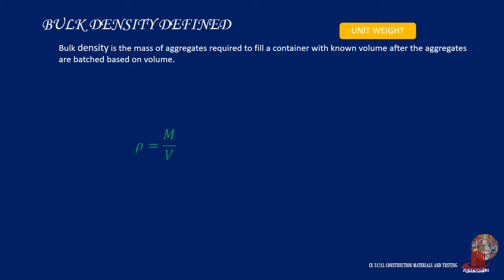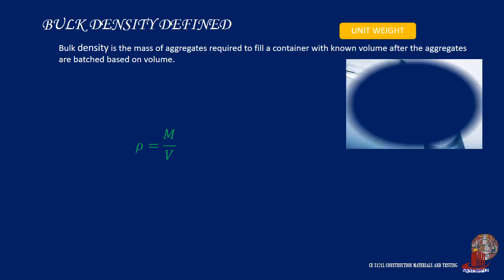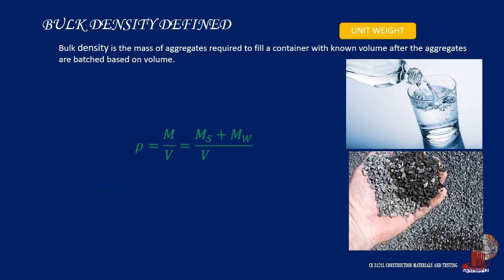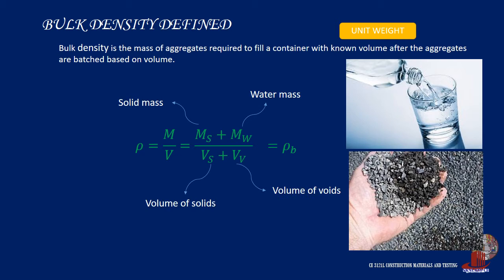The formula for bulk density is derived from the general formula of density, which is the ratio of the mass to the volume. However, unlike in fluid mechanics, where the material is homogeneous and taken as one, aggregates properties would have to be separated between the solid and its moisture content. At their natural state, the presence of moisture is considered in the aggregates, so bulk density will then be computed as the ratio of the summation of mass of solids and water to their volume.